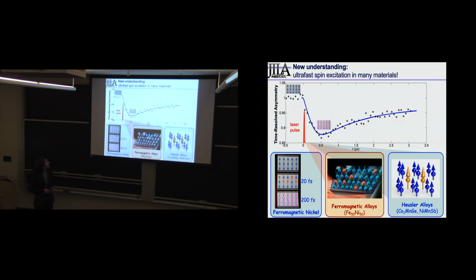So what we've found is that using this ultrafast electron calorimetry, we see fast spin excitation in any material we've tried. That does not mean we've tried anywhere near enough to know that this is general, but essentially we see it in simple ferromagnets, in alloys, Heusler alloys, that the spin excitation happens instantaneously, or with the light excitation. But you make these exotic excited states that are hard to see.